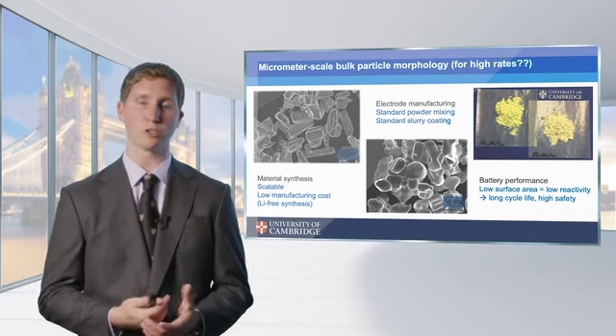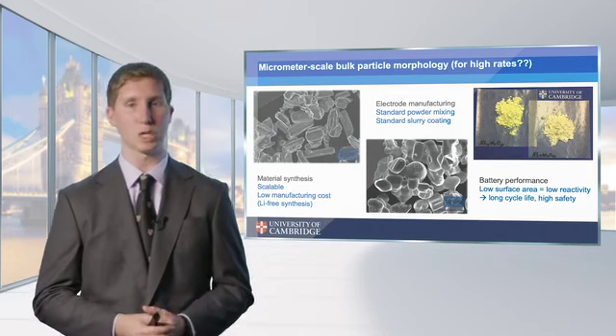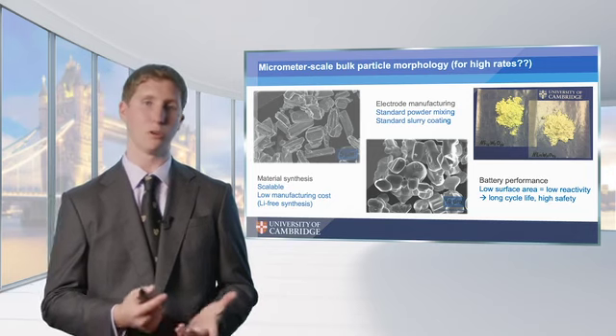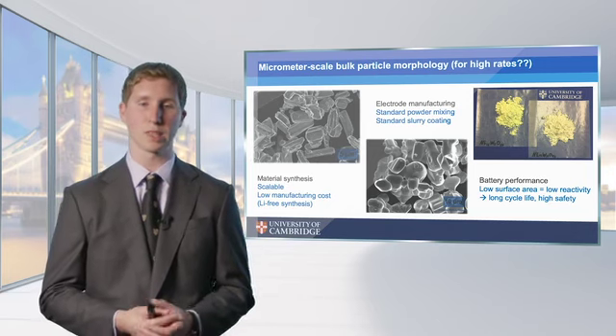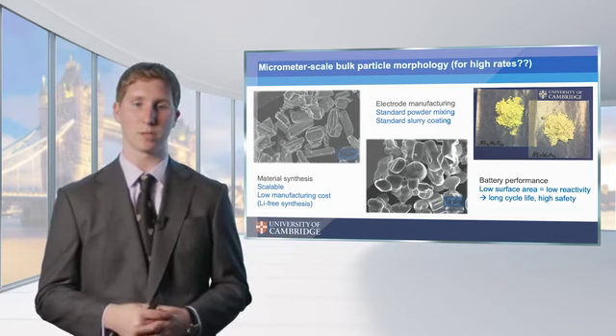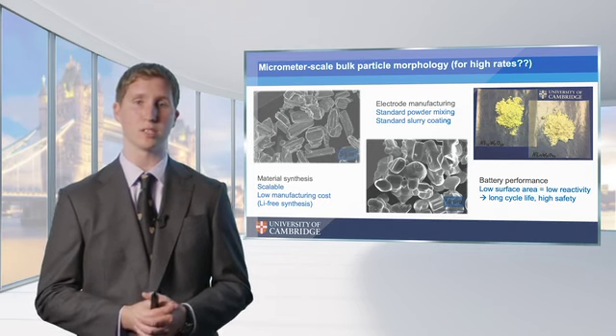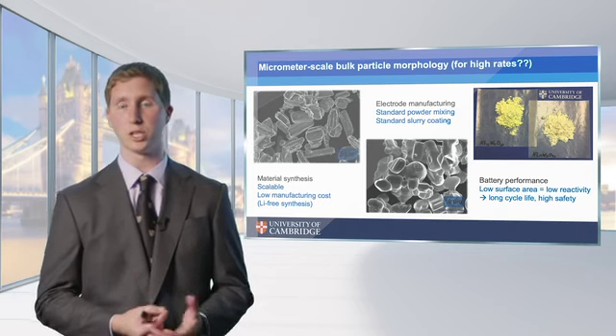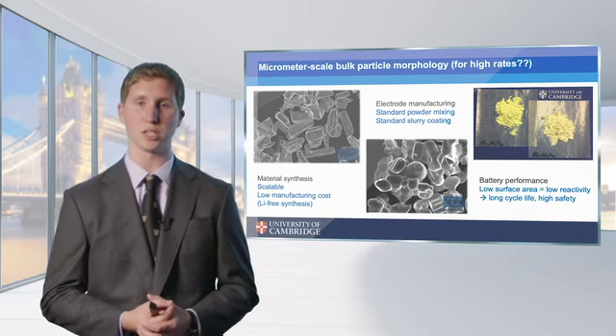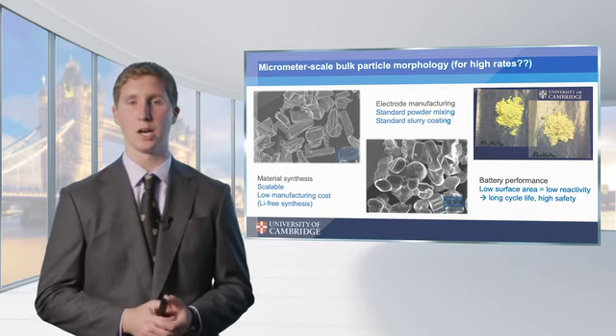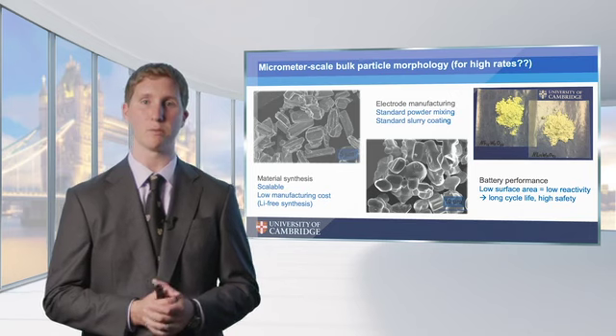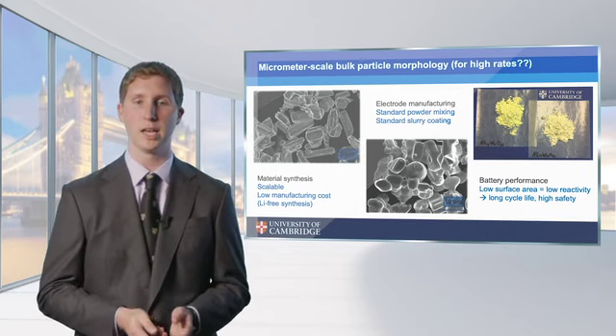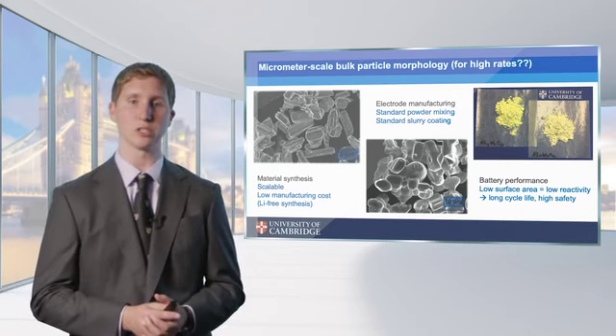And there's a low manufacturing cost associated with that because we don't have to do any complex hierarchical or nanostructuring to these materials. And as a side note, conversely to LTO, this is a lithium-free synthesis. And so we avoid the issues with lithium volatilization and getting those lithium contents just right at the high temperature synthesis of LTO. And so that makes our material synthesis a bit easier and cheaper.